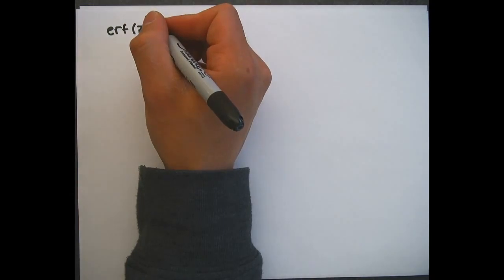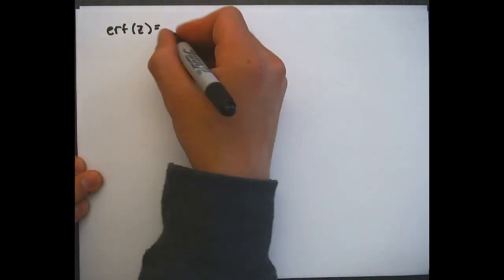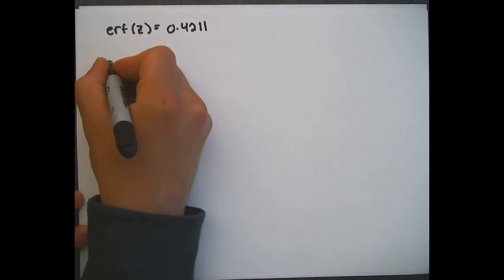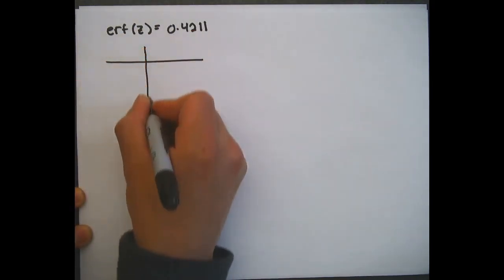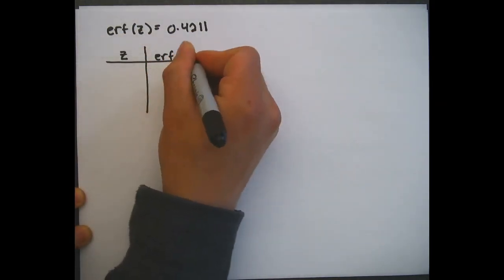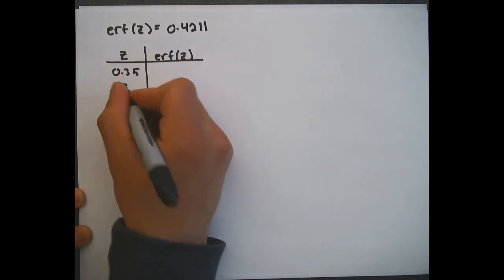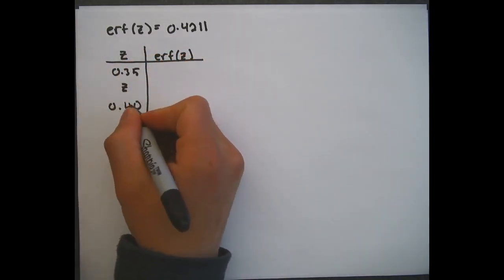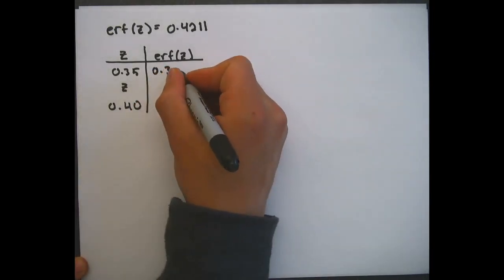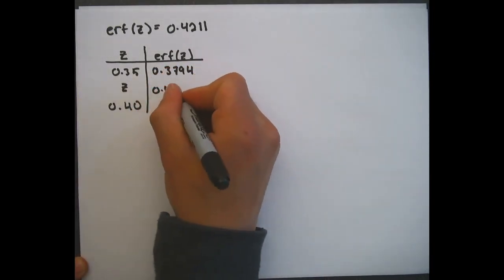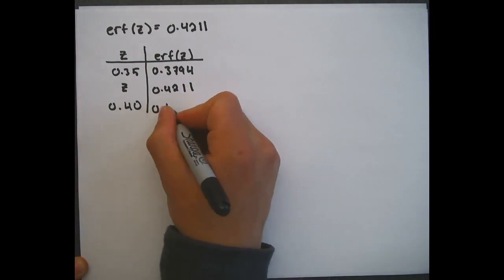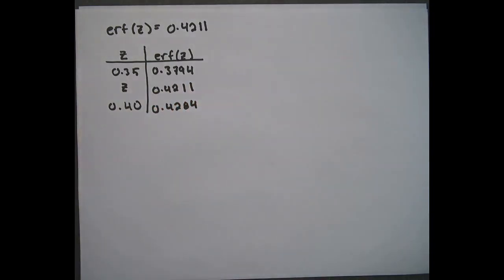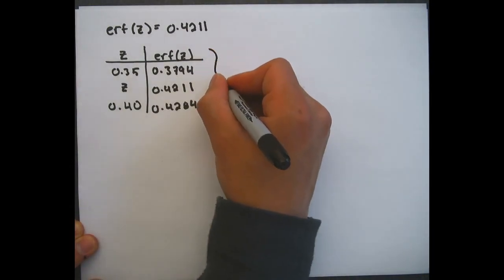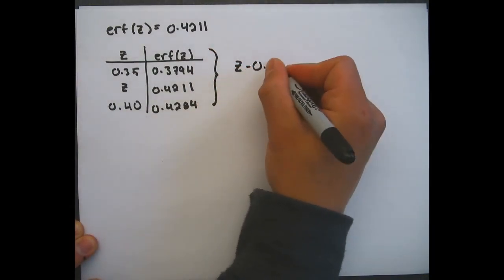This is going to come in very handy in just a little bit, you'll see. Earlier on we found the error function and what it was equal to. We replaced x over 2 times the square root of Dt with z. I told you it'd come in handy. So we make a new table with our z and our error function of z. Now we have our value of the error function of z, so we find the two points it lies in between. We leave our z as variable z, and set it in between the two z values, in between the two error function z values.